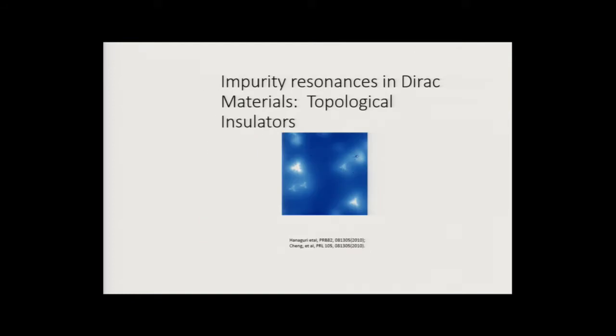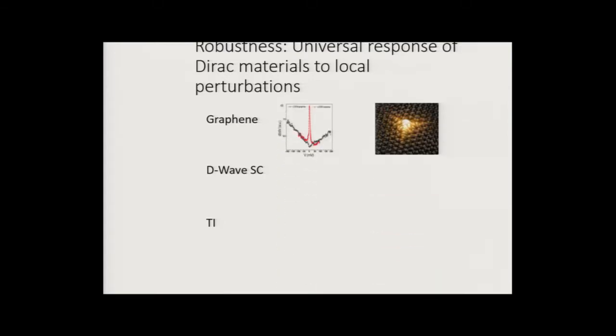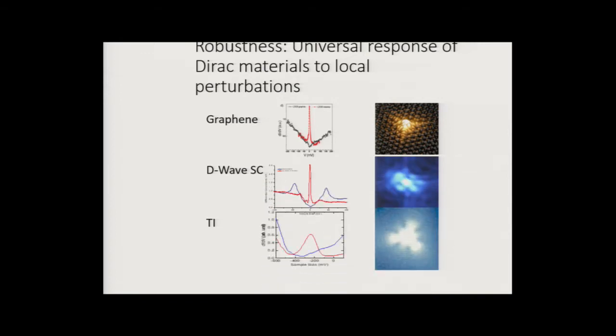Then, impurity resonance is also seen in Dirac materials, in topological insulators, ubiquitously. So even though a topological insulator is supposed to be very protective against backscattering, you do have impurity resonances showing up. So, therefore, actually, I will just put it out there. My point is that there is a robust universal response of Dirac materials to local perturbations. Namely, if you take graphene, if you take a d-wave superconductor, if you take a topological insulator, in all of them you have this impurity states inside the node or near the Dirac point.